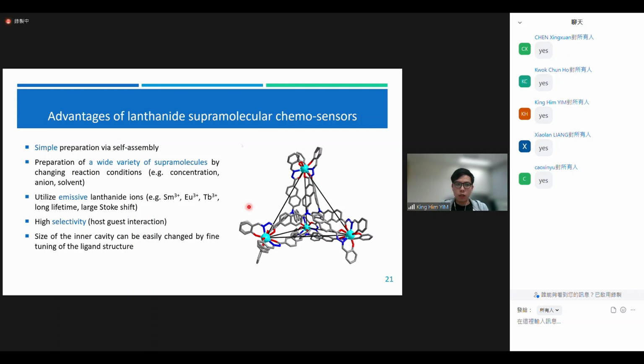Another key advantage is the preparation of a wide variety of supramolecules. This type of supramolecule is governed by many different conditions. For example, if you change the concentration, the cation, the anion, or even the solvent, it will give you a very different supramolecular product. That means you can prepare a wide variety of supramolecules using the same ligand and same metal. And also, the lanthanide is emissive, and as I said before, it exhibits very unique photophysical properties, such as long lifetime and large Stokes shift. Using this kind of emissive lanthanide ion is very useful for preparing fluorescent chemosensors.